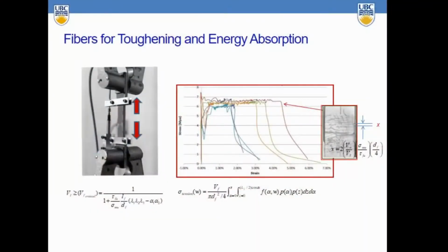We are also looking at much greater strain capacity. Some of you probably understand steel. Steel has an elastoplastic response. What we are looking at in these systems is a typical ECC, where you can get up to, say, 4 to 5% strain in the material itself. So not only are we making them durable, we are also making them much more energy absorbing, or much tougher, with a much greater fracture toughness. If you follow fracture mechanics, we're looking at a much greater R curve, or much better G sub C values. It means it will absorb much greater energy before it collapses or fractures.